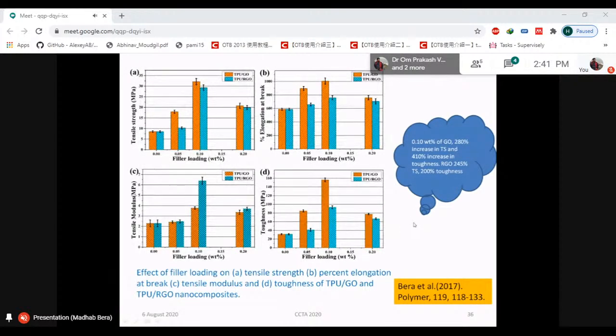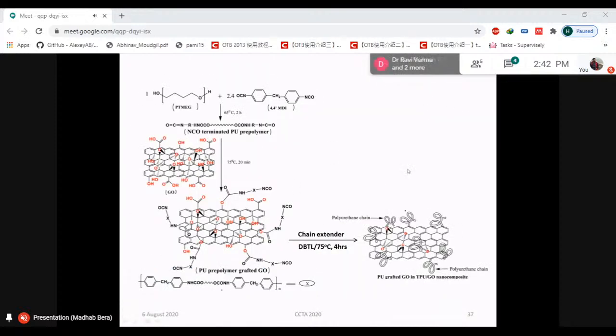Now, if we add two different types of nanomaterial, one graphene oxide and another reduced graphene oxide, into the polyurethane matrix, then we will get different degrees of improvement, because, as I told and showed earlier, of different degrees of interactions between the polymer and filler. With the incorporation of 0.1% GO, 280% improvement in tensile strength and 410% improvement in toughness is observed. But if we incorporate a similar amount of RGO, then we find 245% improvement in tensile strength and 200% improvement in toughness. That means with the incorporation of GO or RGO into the polyurethane, it improves not only the tensile strength but also the toughness of the material. So this is the interactions.